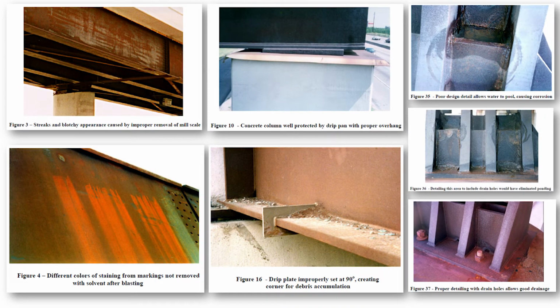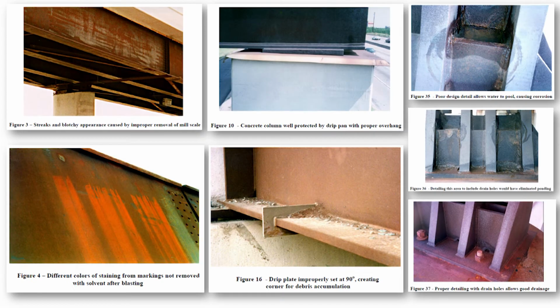So you want to use them for your stain control, but you need to be careful to put them at an angle. Similarly, in the top middle, we found that drip pans work very well. If you look there, you see a pier cap that's exposed to the elements, gets a lot of rain, gets a lot of cycles, but the drip pan does a good job of keeping the stains off the concrete. And it doesn't go very far past the edges of that concrete, so they work very effectively. But again, you've got to be careful about ponding.